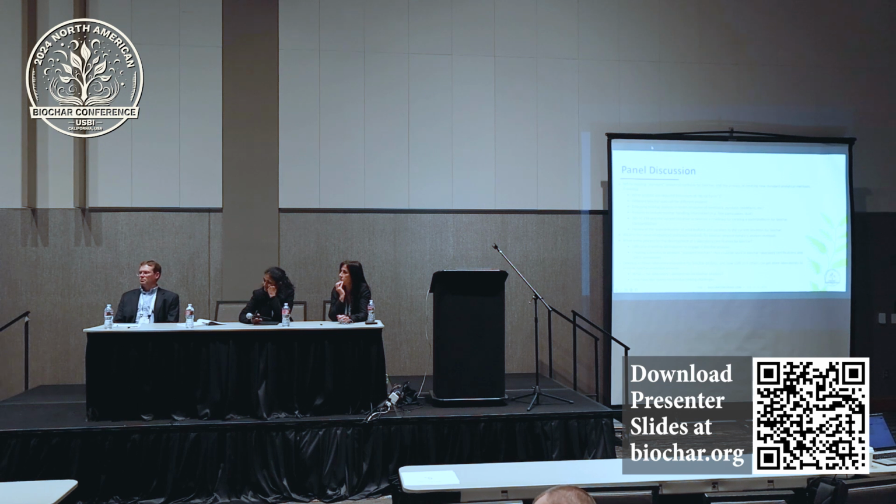Now I'd say I'm not completely sure. I'm pretty sure I want a lot of surface area, because usually more surface area means more places for stuff to stick. Therefore, I probably want something with smaller pores. Smaller pores mean more surface area. But there's also how biochar ages in the environment and how quickly it ages, and all of those things. So I've come to the very humbling conclusion that I'm going to have to test it. And that'll depend on which metal, and which water it is in.